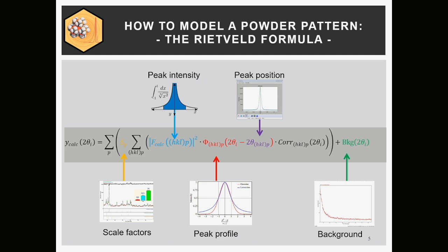So you have to build up your peak from principles, from fundamental parameters. Or you have to have, let's say, a working model, as Paolo mentioned today in the morning. He said you have to have some phenomenological model. Phenomenological means it works. It's not physically based, but it works, okay? So you need a very good peak model, and all these peaks must be normalized to 1, of course. You do not want extra intensity when you sum up the peak. If you just sum up the peak as it is, it should sum up to 1, and then this is multiplied, of course, by the intensity of the peak. So normalized models,